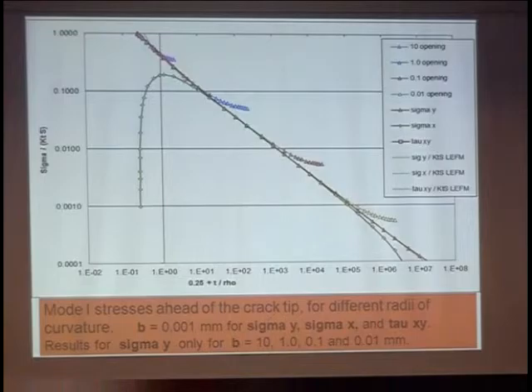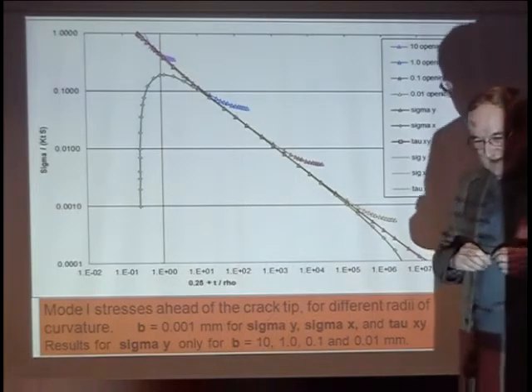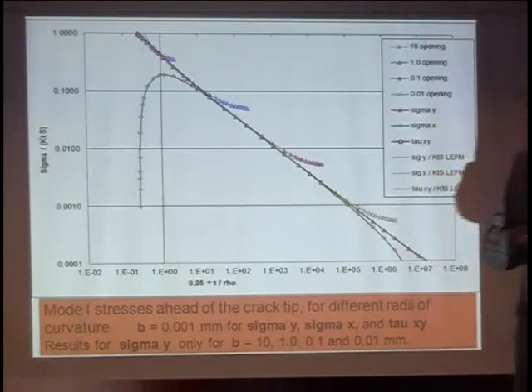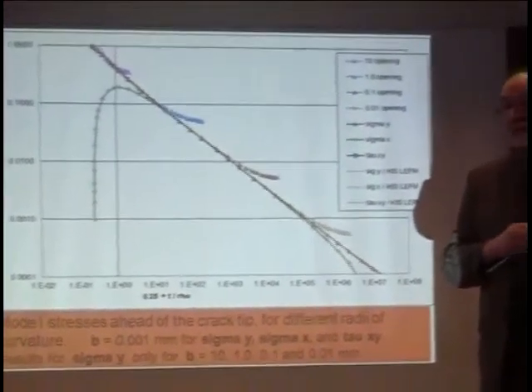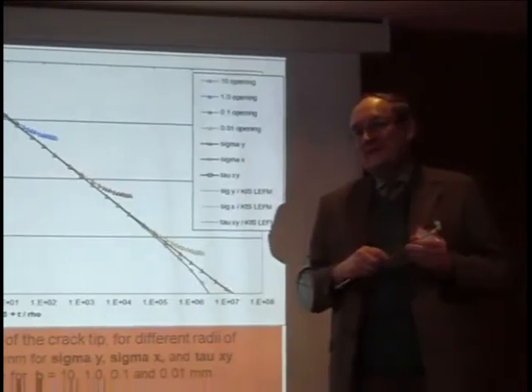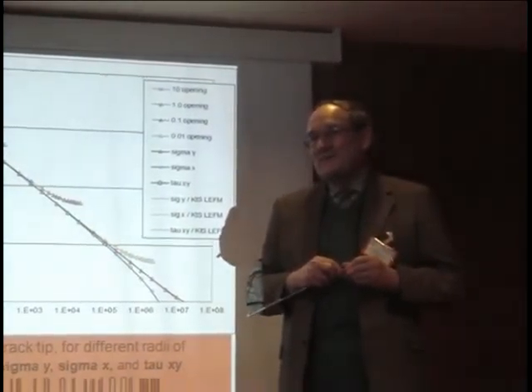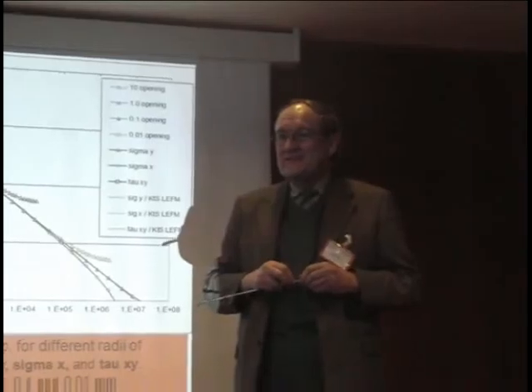The Japanese paper which you have cited, they get this pure mode 2 crack growth only under compression load or without compression? As I skated over that a bit, if you're going to look at steels, then you found you needed to put this compression load on. Much of Otsuka's early work was on aluminium alloys, and then the compressive load wasn't needed. For some reason, because of the characteristics of the steel, we found that they're more likely to branch, and therefore we had to put on these clamps to stabilise the growth.